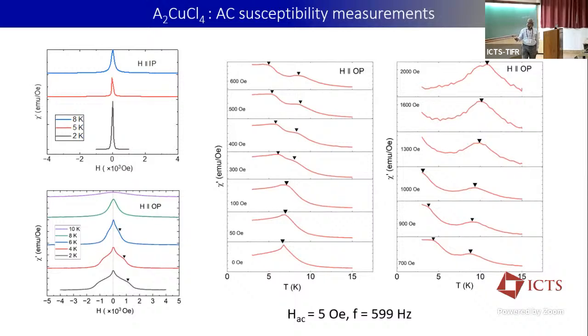As you are increasing the field, two peaks appear, and when you go to very high field, it is again one peak. That means there is some magnetic transformation. There are many states, and as you apply the field, the magnetic state evolves as a function of the magnetic field.